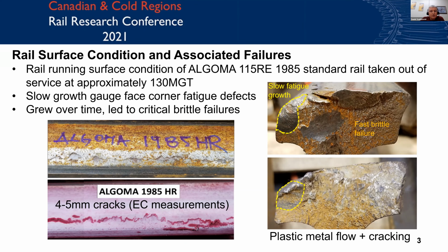So over the course of the lifetime of this rail in track, it accumulated 130 mgt of traffic. It had a limited amount of grinding. As far as we know, it was ground just once or twice. The last time was in 2005. And as a result, with the accumulation over the last 15 years and no grinding, the result is what you see on the right-hand side. That's the type of plastic wear that exists in a high rail of this grade when there's no grinding.